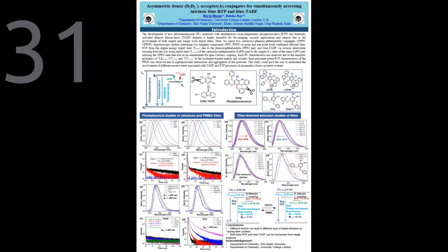We studied the molecules in different mediums like solutions, polymethyl methacrylate film, DPPO film, and concluded via time-resolved emission studies that thermally activated delayed fluorescence is observed from the lower charge transfer state, while RTP is observed from the higher lying locally excited triplet state.